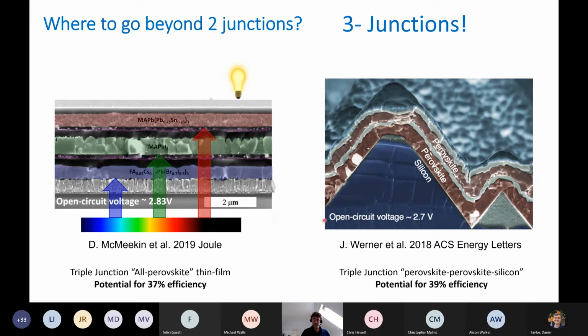This is an example of a silicon cell which is textured with pyramids, where there are 2 perovskite cells processed on top. In terms of absolute efficiency, these triple junction cells haven't delivered very high efficiency yet. It's very difficult to get all the layers processed on top of each other and choose the right layers, but there's been very little effort in this.